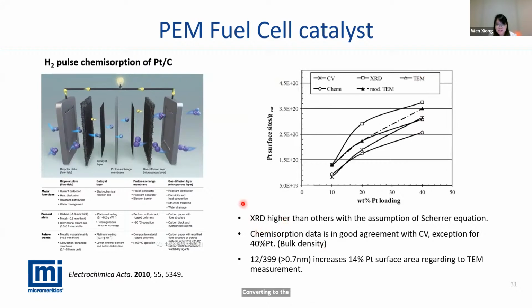That's because XRD has higher results than the others, as they use an assumption from the Scherrer equation. And as we all know, for the TEM data, we have to collect a lot of particle numbers. It's a lot of work to do the calculation to get the platinum surface size. So that makes sense. Chemisorption is a good, easy, simple, quicker alternative to get the platinum surface size, and also, like I said, without any assumption.